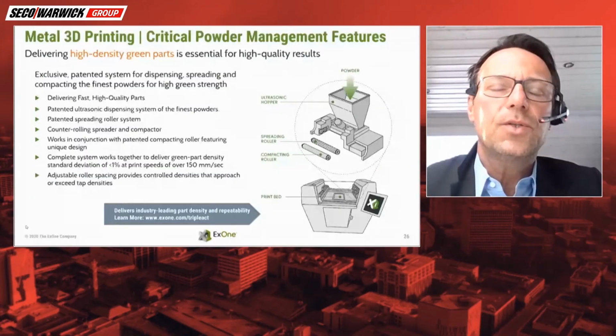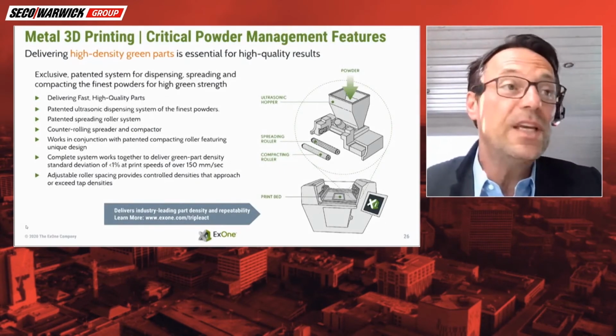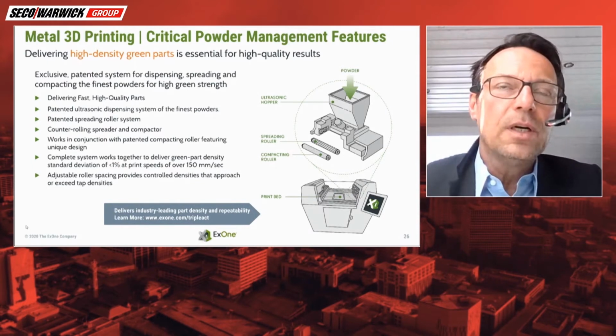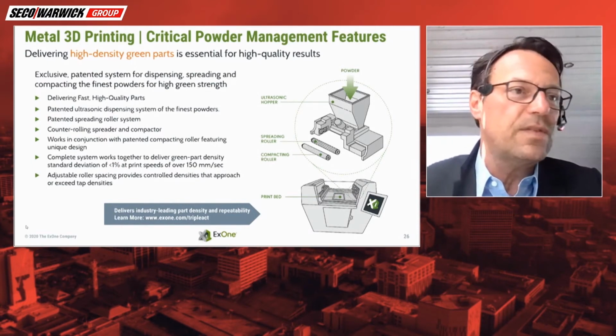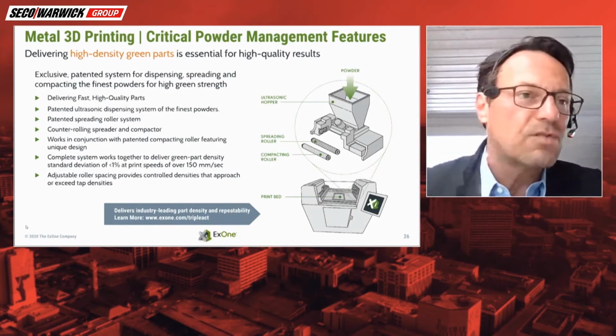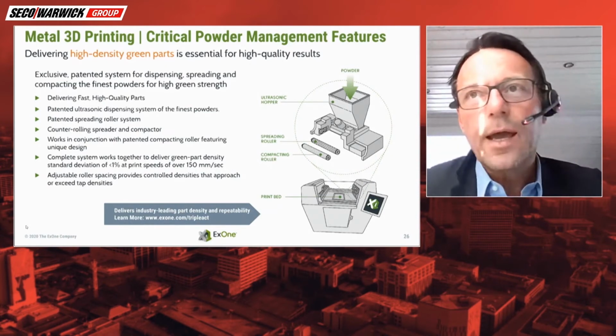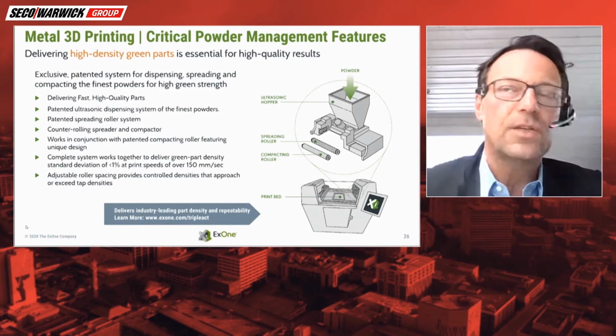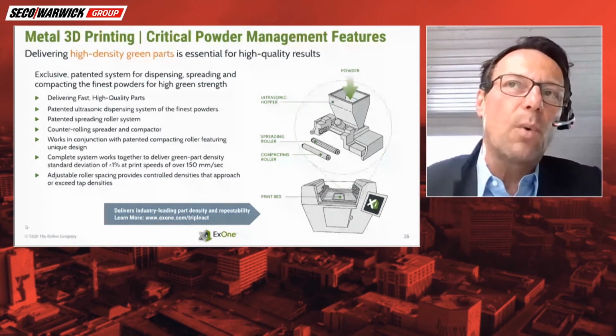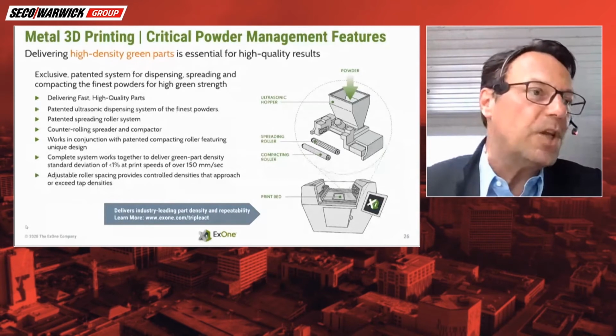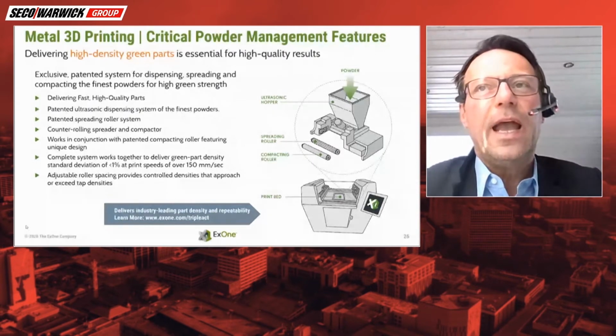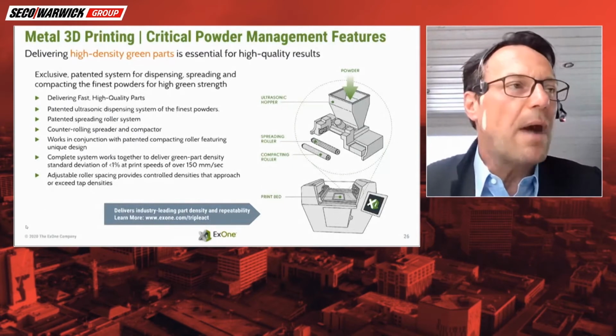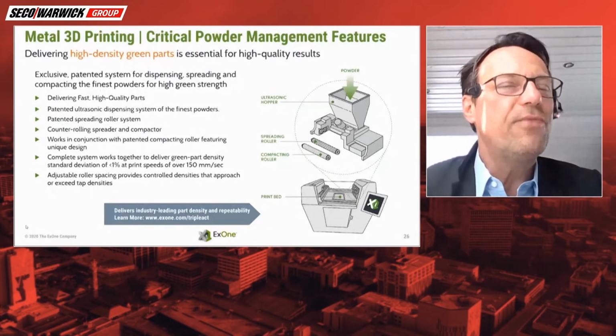The ACT technology enables us to handle a powder, and we have learned from Mark's presentation there is a lot of difference in powders, and I can tell you he's so right. The powder people are more familiar with, the most optimal powder, is very spherical. There are no satellites, it's flowable, and all these things. But at the end, if you want to go into a more productive way of producing binder jetting, you try to go for MIM powders, metal injection molding powders, which typically have a D10 of 22 microns. That means it's quite a very fine powder.